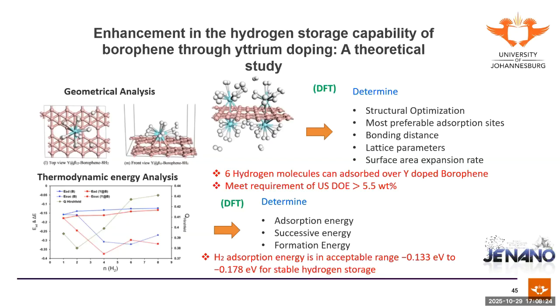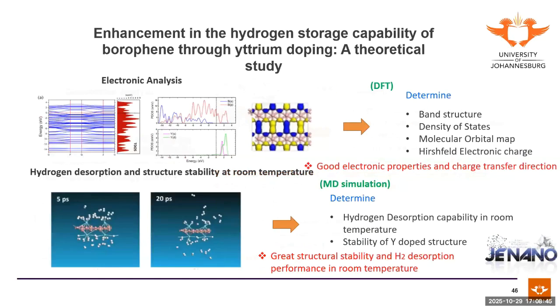Another is the thermodynamic energy analysis, and we find that the hydrogen adsorption energy is in an acceptable range, minus 0.133 eV to minus 0.178 eV, for stable hydrogen storage. So this is another very positive result. Then we further did the electronic analysis, and it shows good electronic properties and good charge transfer directions. Then we did the MD simulations, and we see great structure stability and H2 desorption performance even at room temperature. I think this is very important because you want both absorption and desorption, especially at room temperature.